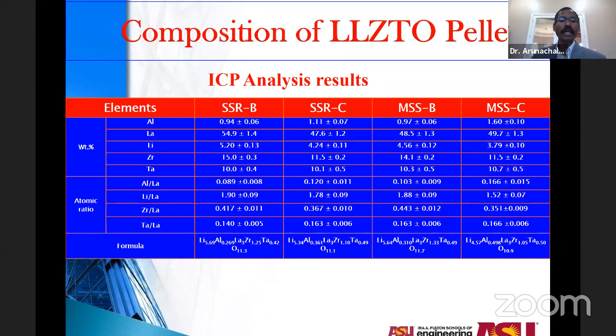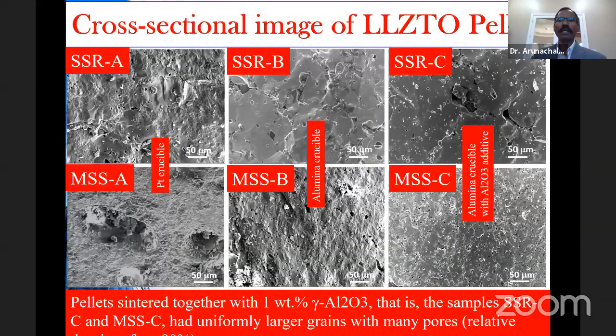And the cross-section again is very important, right? Like I said in the beginning, one of the important characteristics required for the solid electrolyte is an almost pore-free cross-section. You can see that the ones on the left-hand side are pellets sintered in the platinum crucible, for both the powders made by solid-state reaction and the molten salt method.